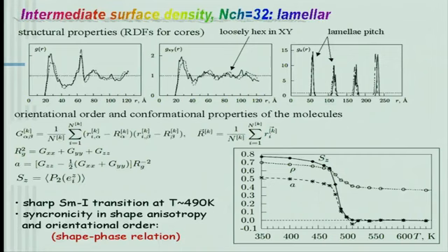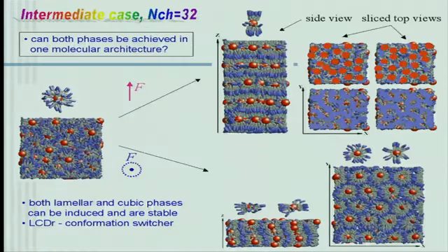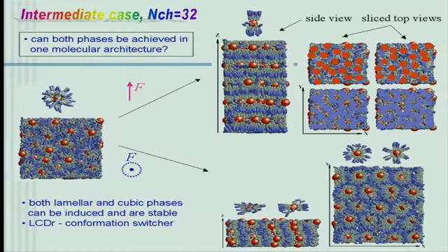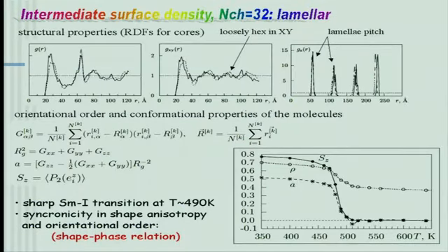And here I would just like to show some radial distribution functions, evaluated for the lamellar phase within the layers. We thought maybe we have some hexagonal packing, but it is rather not well defined, I would say. And in that direction we have a very clear indication of the layers. We also calculated the orientational order parameter, which was of the order of 0.7.